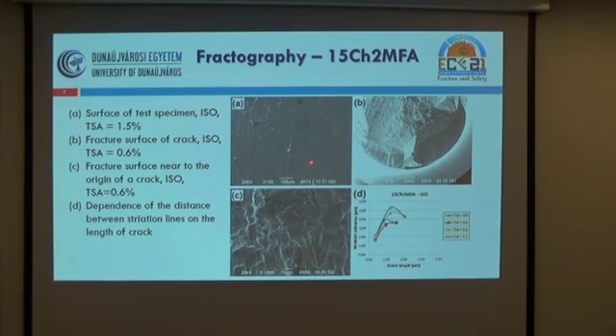This is the surface of the specimens when the total strain amplitude was 1.5. I'm not sure that it is well visible, but you may see some network of the initial cracks on the surface, and then there is the fracture surface, all in the isothermal fatigue. And in this picture, you can see the fracture surface near the starting position of a crack.